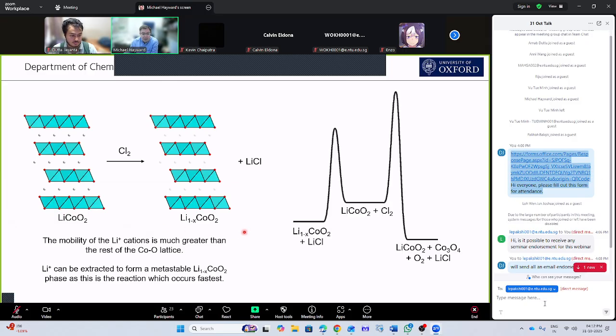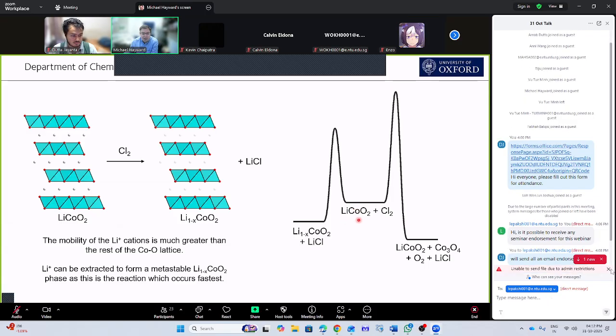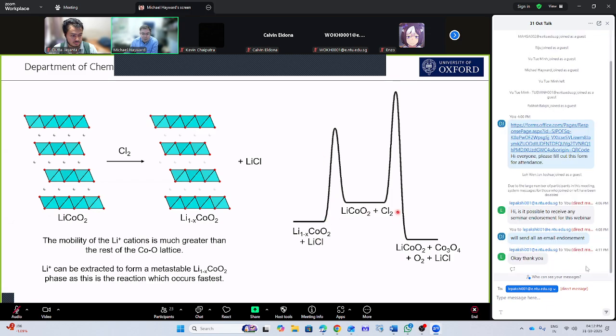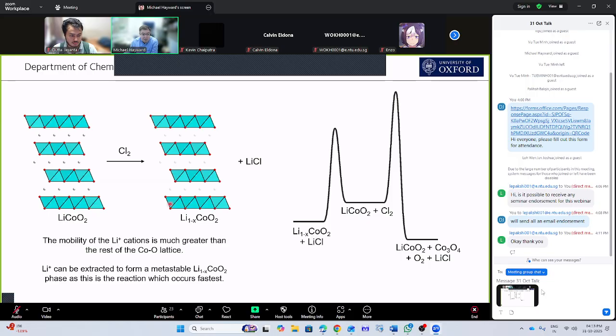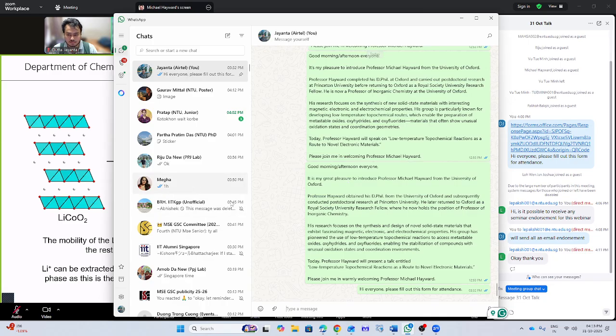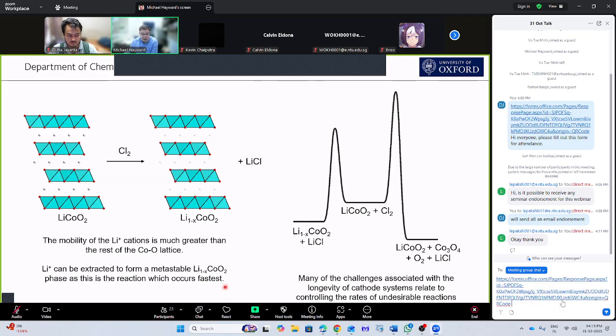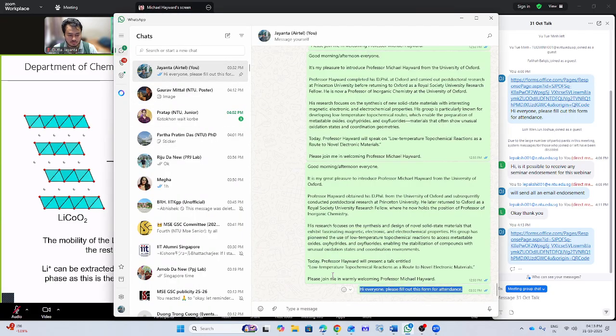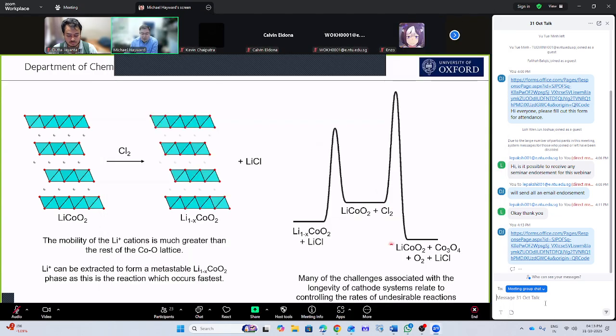And what this means then is that the activation barrier to turn LiCoO2 into Li1-xCoO2 is much lower than the barrier to form the thermodynamic products, which are a decomposition reaction to cobalt oxide and lithium chloride. And so we can use this idea of the different mobility of the ions leading to different reactivity of the ions to think about making metastable materials. And actually in the lithium ion battery research area, most of the challenges arise from controlling the size of these activation barriers so that we can choose to go over this one selectively rather than a variety of different decomposition products.